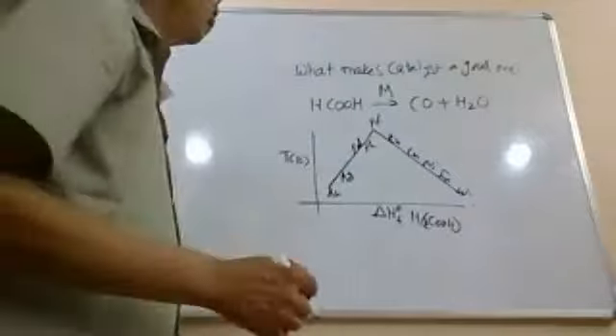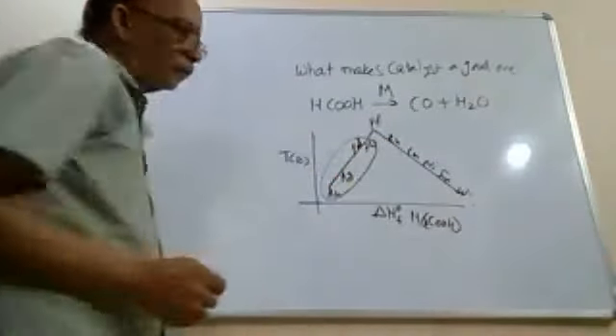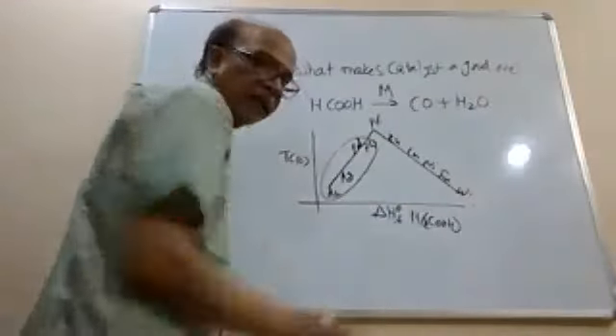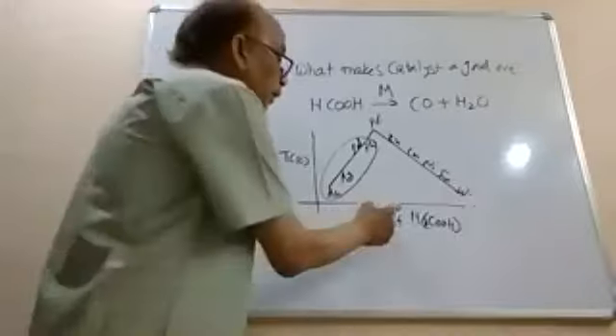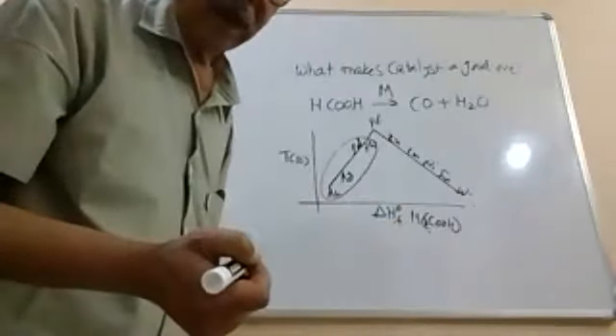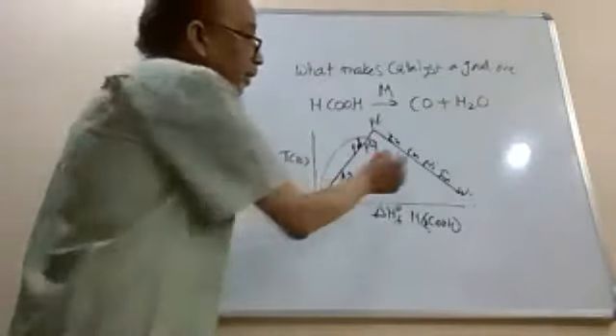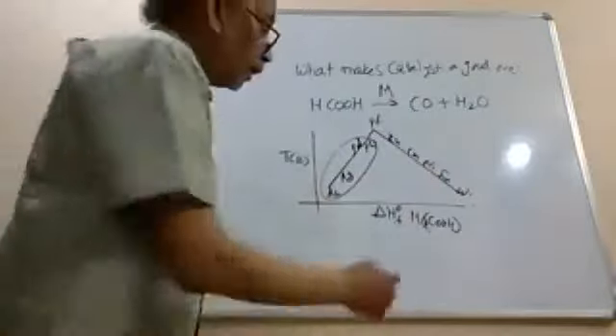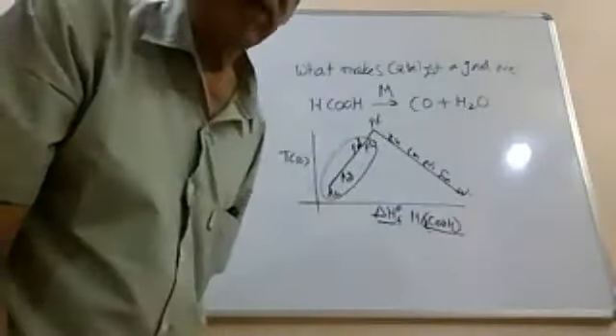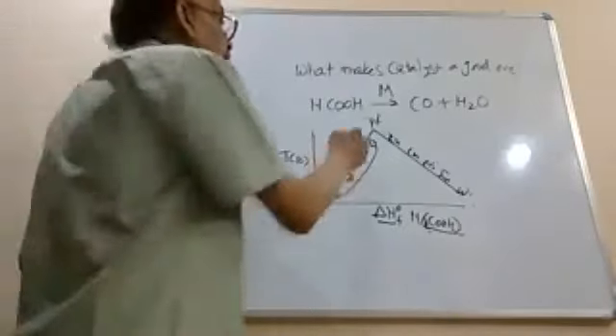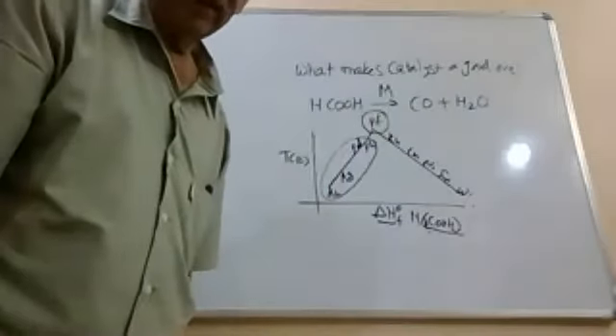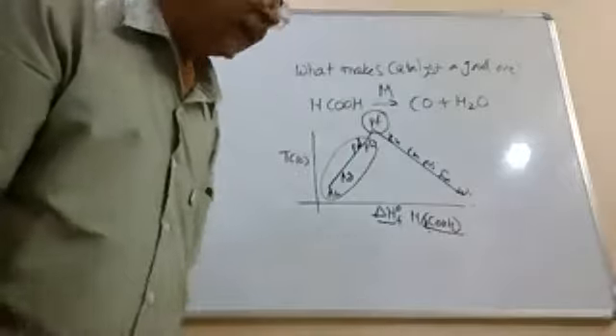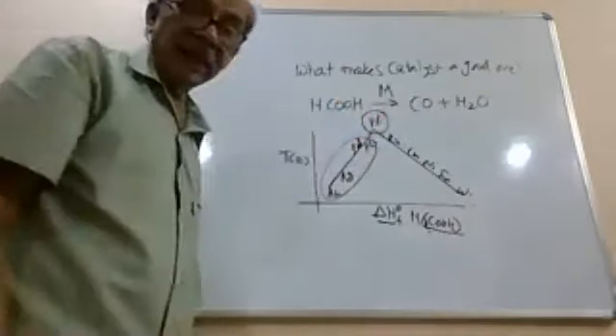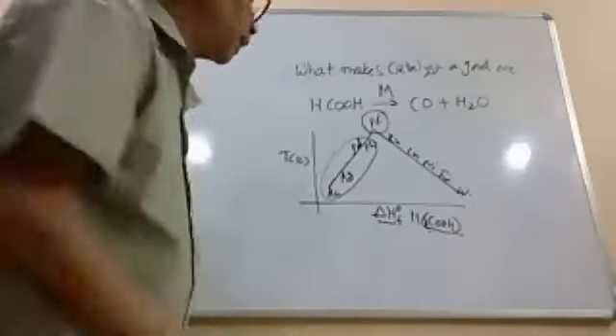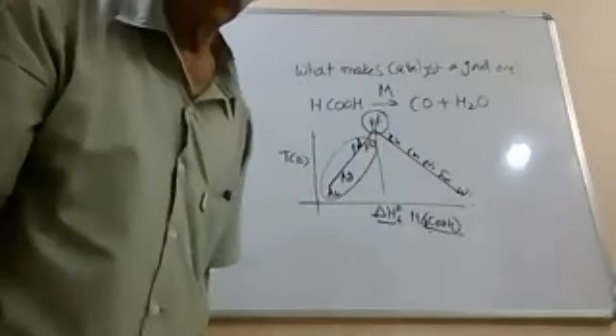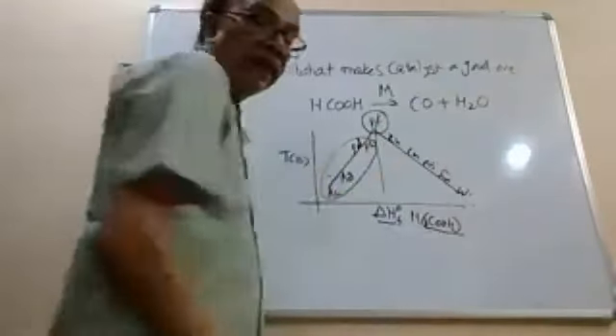What is happening here is metals that have very low heats of formation, that means the affinity between the metal and the formic acid is very small, those are not good catalysts. On the right-hand side of your volcano, you have transition metals that have very large heats of formation. They are not good catalysts either. So what you want to have is one that is moderate, neither too small nor too high. So in the decomposition of formic acid, people find platinum is a superior catalyst because platinum has the right heat of formation, neither strong nor weak relative to other elements.